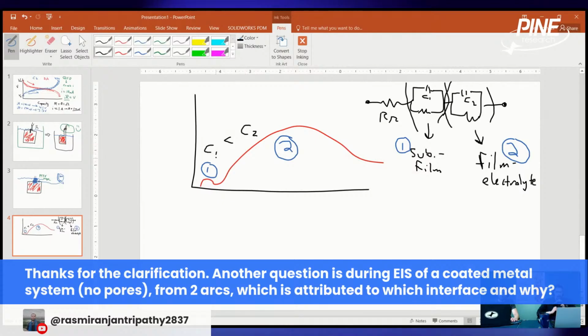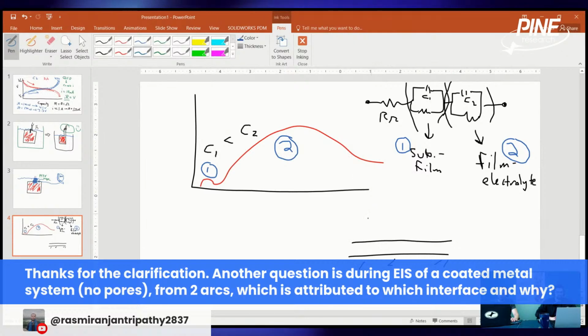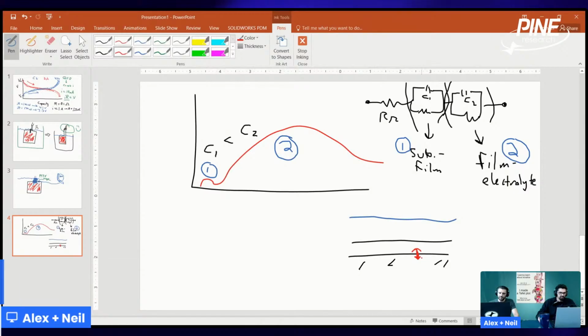The reason you're going to see it this way is the capacitive element, if there is any, between the substrate and the film. You said there are no pores, so you basically just have this interface between your substrate, your film, and then your electrolyte. The interface here between substrate and film, I'll just draw a little arrow here. There's a capacitance associated when any two dissimilar metals are there, some interfacial capacitance.